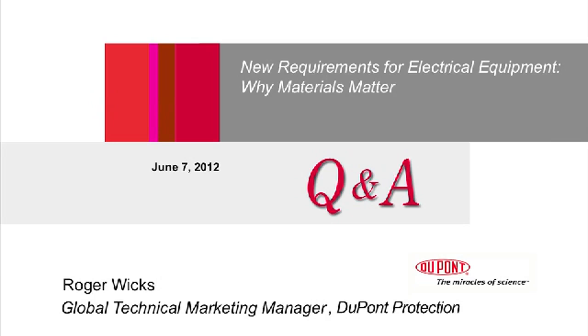What is the shortest aging time that should be considered in order to achieve the equivalent of one IEEE life? Gee, that's an interesting question. Again, a lot of it depends on the requirement that you're doing the aging for. Most of the IEEE test protocols were established based on 20,000 hour life. And in such an evaluation, we like the shortest time to be around 100 hours and the longest time to be around 5,000 hours. In the case of what I mentioned earlier where we're looking at 20-year life, we're